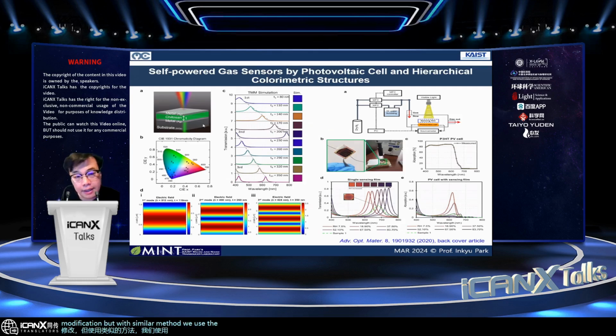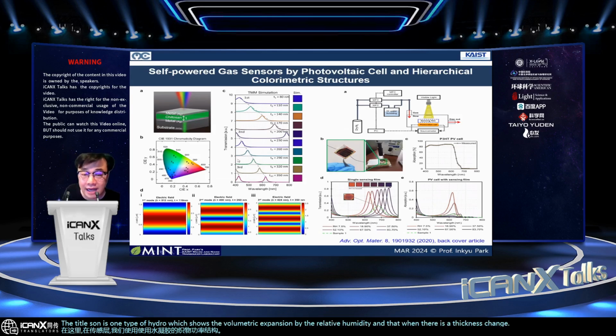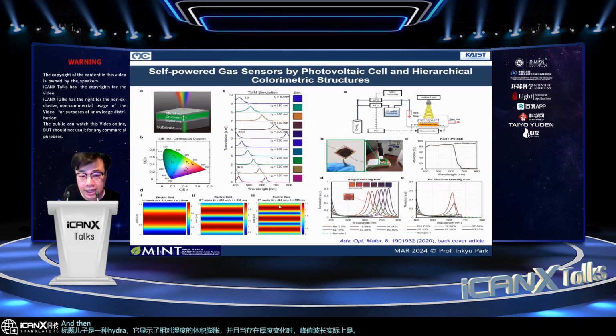We use the current output from the solar cell, but here for the sensing layer we use a Fabry-Perot structure using a hydrogel. Chitosan is one type of hydrogel which shows volumetric expansion with relative humidity, and when there is a thickness change, the peak wavelength changes, and then you can detect that by the solar cell output.